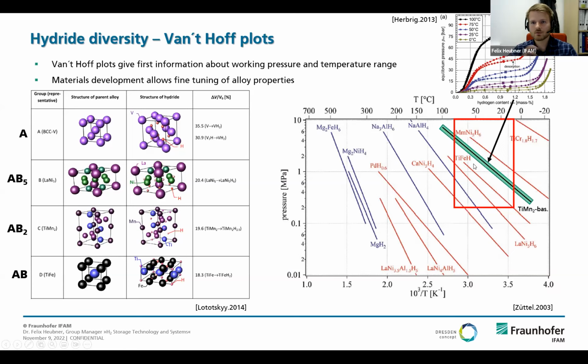And there are different values for absorption and desorption available. So we have more like a corridor for each material, not only a straight line. So this is titanium manganese based. We have some complex hydrides available that have a higher gravimetric storage density, like sodium aluminum hydride here, or some magnesium nickel based hydride, or even pure magnesium hydride operating at higher temperatures.